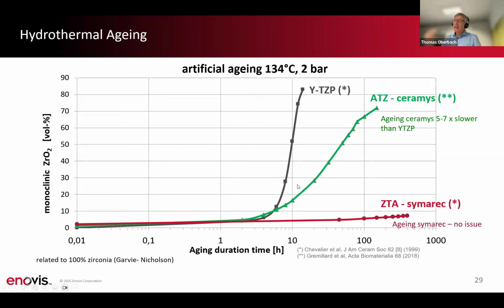In the literature, you can find that 1 hour aging corresponds to 1 year, and this is a logarithmic scale here. And if we look on this curve for the Y-TZP, then you see after 10 hours aging, which corresponds to approximately 10 years in vivo, we have a monoclinic phase content on the surface of about 50 volume %.